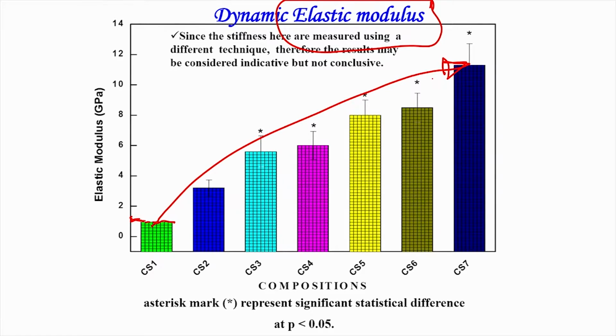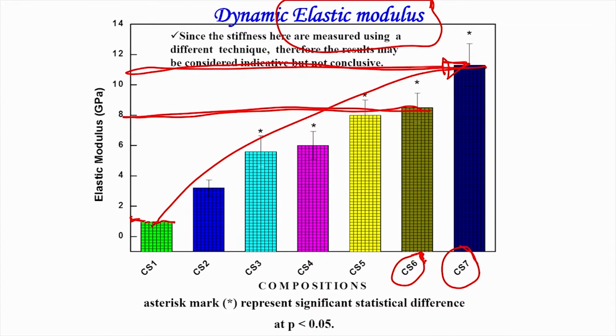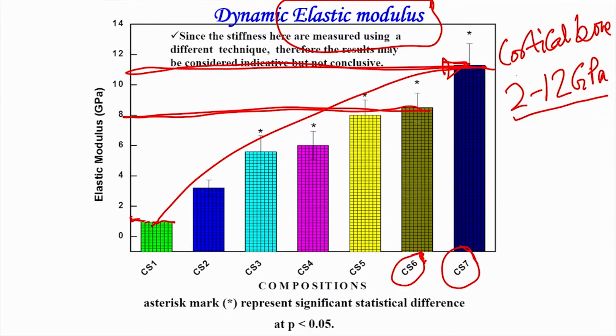If you go to CS7, HDPE HAP 20% alumina with a coupling agent, and CS6, which is HDPE 20% HAP 20% alumina without coupling agent, here you are getting almost 8 gigapascal, and with coupling agent almost 11 gigapascal. So, more stiffness is important, particularly in this window of less than 20 or 30 gigapascal. Why am I saying that? Because cortical bone, that is natural bone structure, has an elastic modulus of 2 to 12 gigapascal. So, these materials, HDPE with 20% HAP and 20% alumina, can well replace cortical bone in this physiological system, or they will have a cortical bone replacement property.